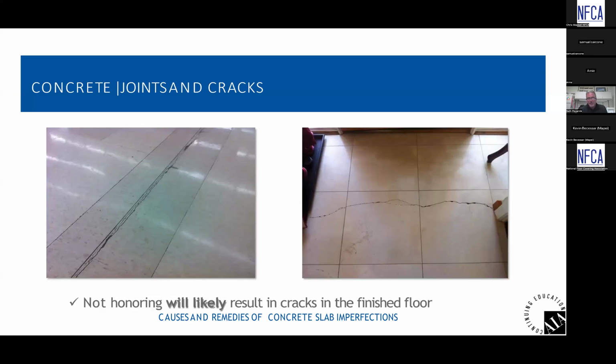So what can happen? If you look at the picture on the left, it's a VCT installation that has been repaired twice, and I say that because not only do you see the joint running down the middle of the tile, but you can see that it's a different lot of VCT going down where the joint is, because it's a different color. So you install over a moving joint, everything looks great until the movement happens, and then the flooring installation does not look so good. On the right, you have a hard tile installation, a crack in the concrete that was not remediated, and the concrete moved and has thus cracked the finished flooring, the tile.